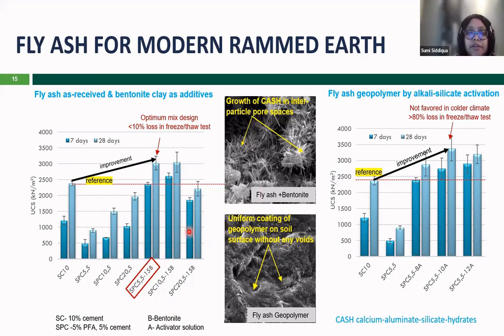So this is how we have looked into the data for 7 days curing and 28 days curing, which is the regular curing, no temperature was added. So we see that's the reference point over here, the dotted line. With the control material with that 10% cement, we saw the improvement with the SPC 5-5 and 1.5% of bentonite. So we saw the increment of the UCS data, the compressive strength data. And with this arrow, we are also saying that we consider that as an optimum mix.